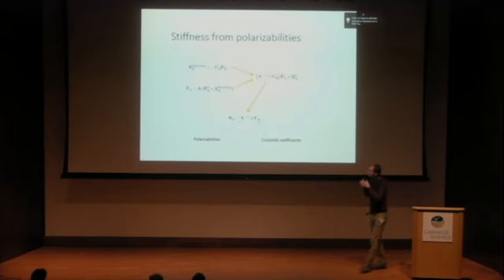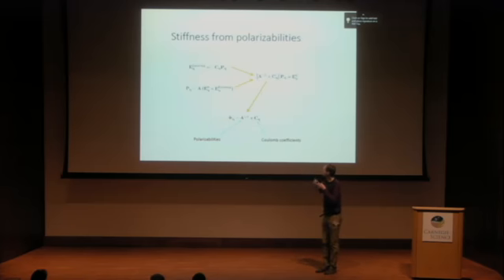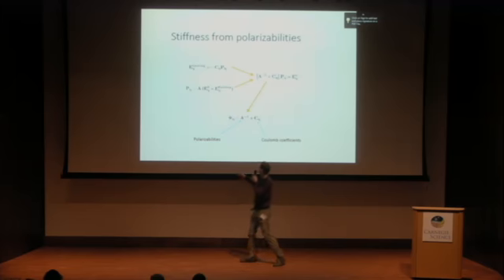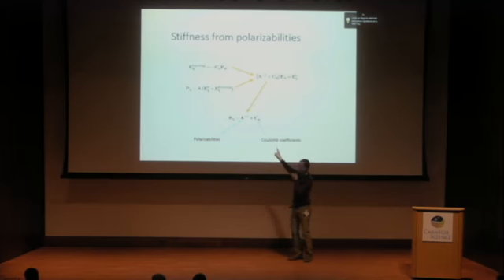And then, by using simple linear relations, we can find the stiffness matrix. And this stiffness matrix is composed of two contributions. One is polarizabilities. These are model parameters. And these are Coulomb coefficients that are not variables, that are defined by the geometry of the perovskite.